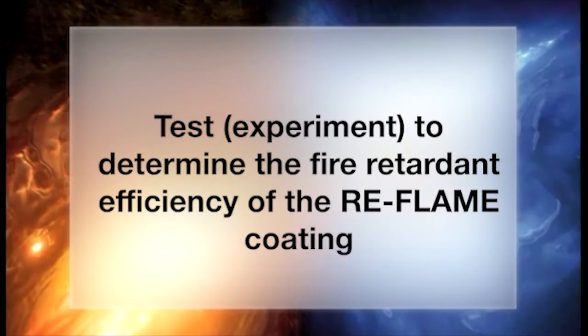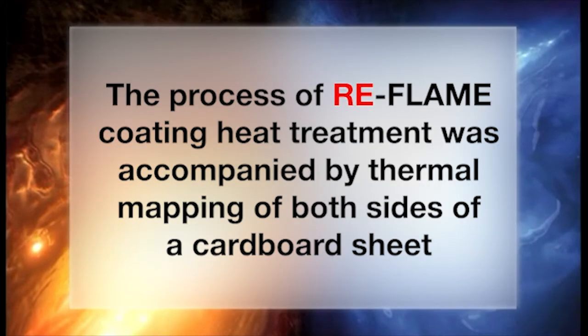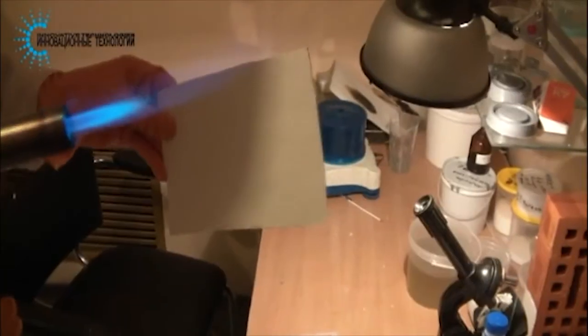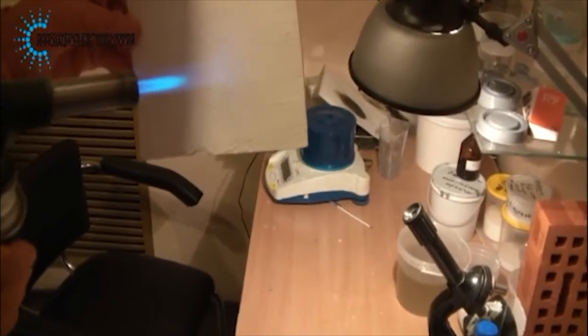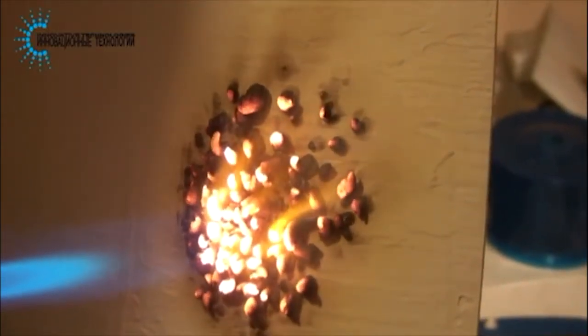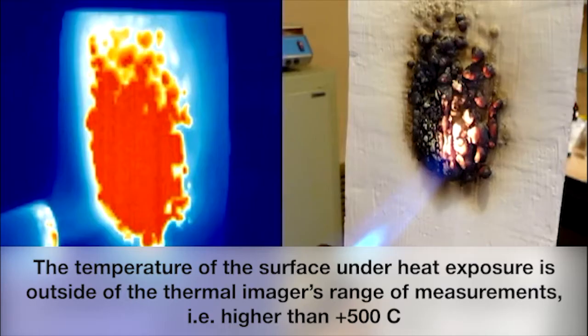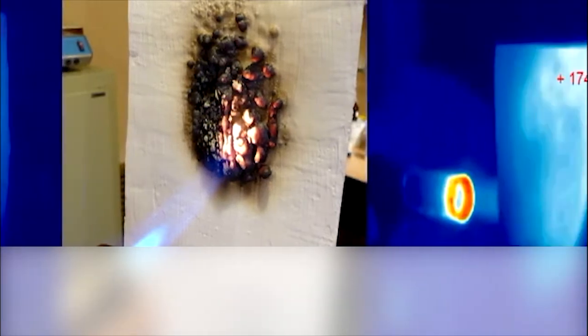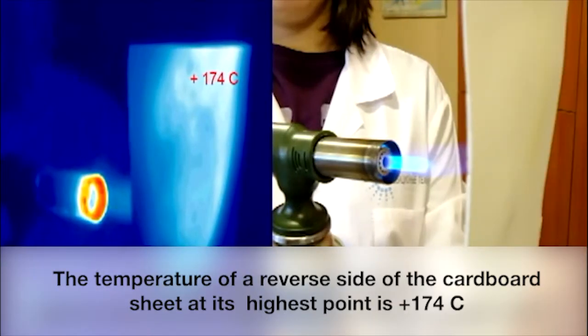Test experiment to determine the fire retardant efficiency of the RE-FLAME coating. The process of RE-FLAME coating heat treatment was accompanied by thermal mapping of both sides of a cardboard sheet. The temperature of the surface under heat exposure is outside of the thermal images range of measurements, i.e. higher than +500 degrees. The temperature of a reverse side of the cardboard sheet at its highest point is +174